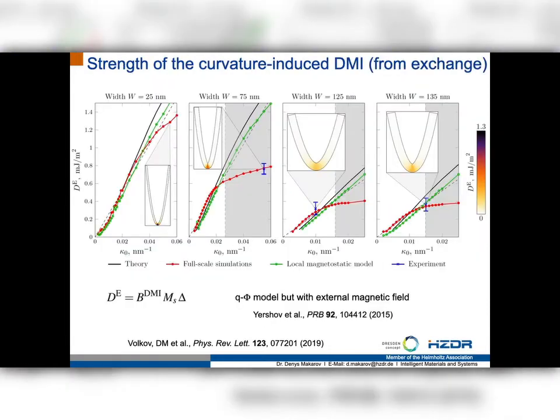Now you can use again the theories which are available in the community in order to relate this switching field which you measure experimentally with the strength of this curvature-induced Dzyaloshinskii-Moriya interaction. It's an effective chiral interaction which you have in this 10 nanometer thick parabola due to the curvature gradient at the apex of the parabola. What you can see here, the blue point, is experimental data which corresponds very nicely with the theoretical analysis. And what is interesting about it is the strength of this Dzyaloshinskii-Moriya interaction which you can get in the system, which is in the order of 1 millijoule per square meter.